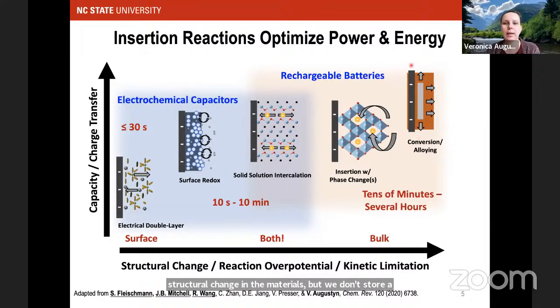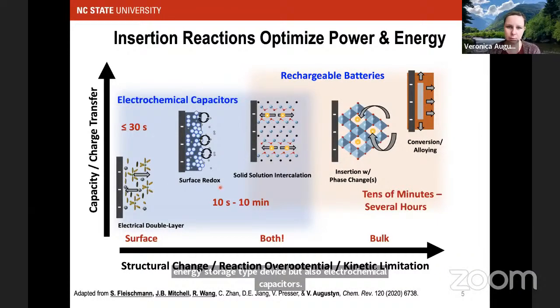On the other extreme, we can have processes like conversion and alloying, where you have significant phase transformations taking place with high capacity. So if you can think about, for example, a bifunctional oxygen electrode, that's oxygen reduction, oxygen evolution. These kinds of mechanisms can provide a lot of capacity, but they're inherently more sluggish. Insertion processes are in the middle. They really are optimizing kind of the best of both worlds. And as a result, for energy storage, they're of interest not just for batteries, which is the most familiar energy storage type device, but also electrochemical capacitors. And these are the kinds of materials and processes that we're interested in.